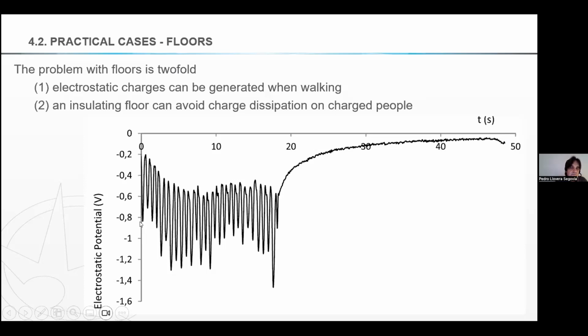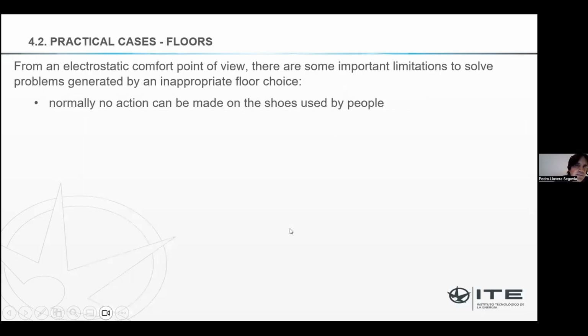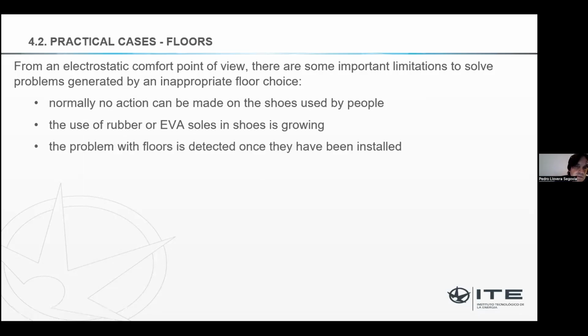Here is not really a big problem. It's around 1000 volts, but we've measured more than 8000 volts easily. So the problem is that normally you cannot make any action on the shoes used by people. You cannot predict what will happen. And more and more in public and commercial areas, the EVA soles in shoes is growing. So rubber and plastics in the soles are increasing the problem.